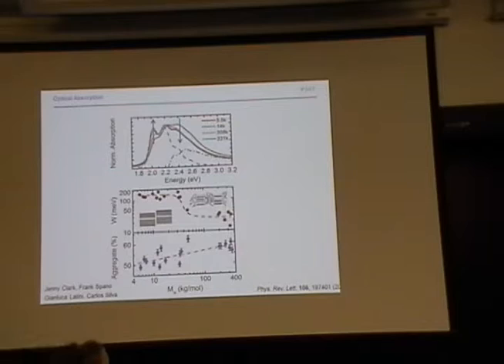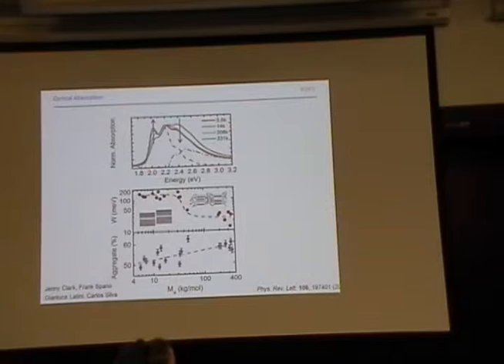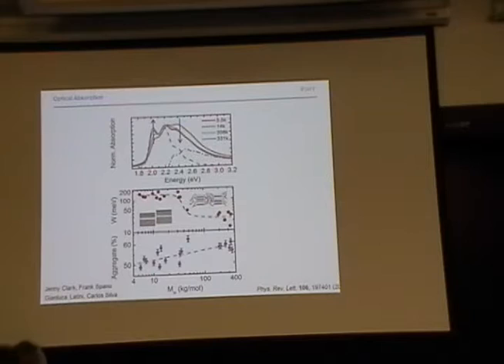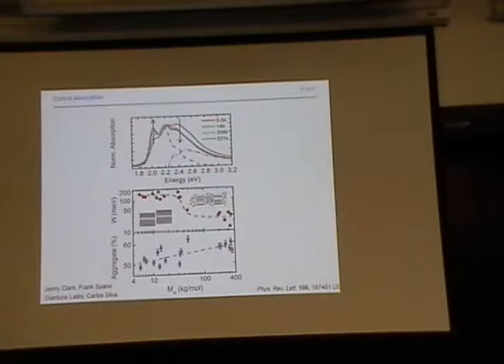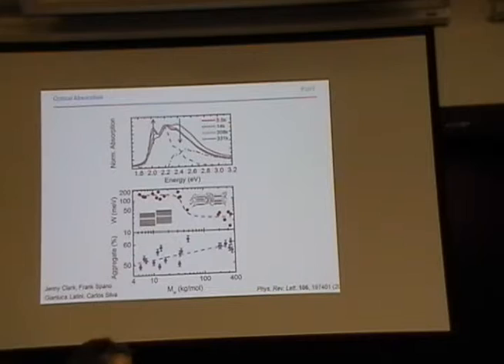It's like a little stretch experiment. In the bulk commodity world, there was a lot of investigation on this strained amorphous phase — meaning you have an interphase of a crystal, a strained amorphous phase which is not fully amorphous, and chains are somewhat oriented to the fully amorphous phase. We tested this hypothesis by using small oligomers with really large end groups like bromine. We see that when we have bromine on both sides, the chains are really, really twisted, then really affecting the free exciton bandwidth. Based on simple UV-Vis measurements, we can get conformational information.